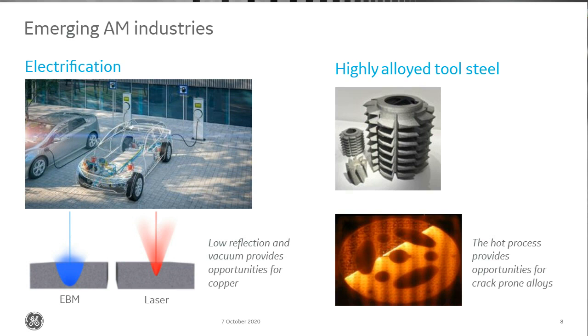If we are also comparing EBM to other additive manufacturing technologies, one of the benefits that we touched upon in the beginning is that the reflectivity of the electron beam is not dependent on the material, it's dependent on the mass of the material. So you can manufacture copper very efficiently with an electron beam, if you compare it to a laser beam, where you would have a lot of reflection of the laser beam from the copper.